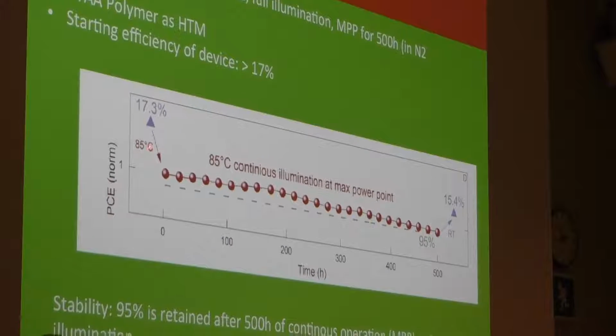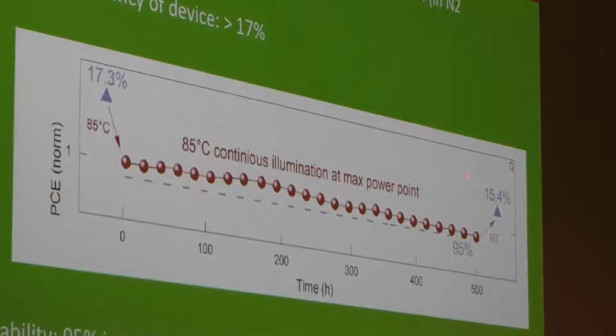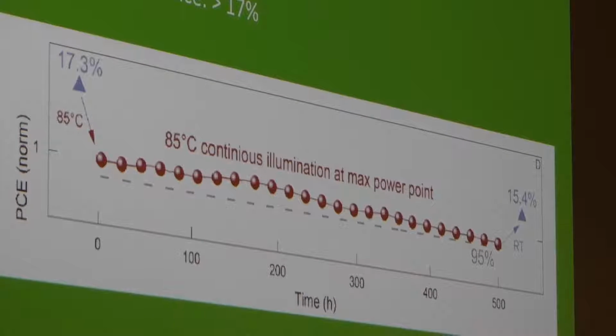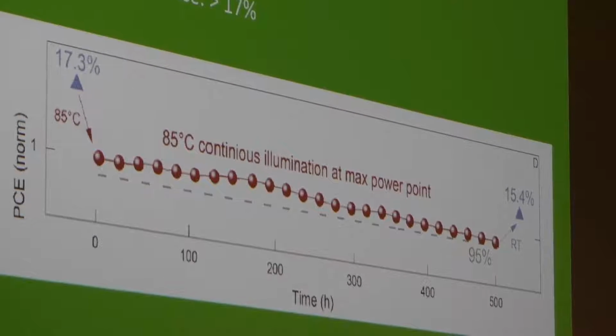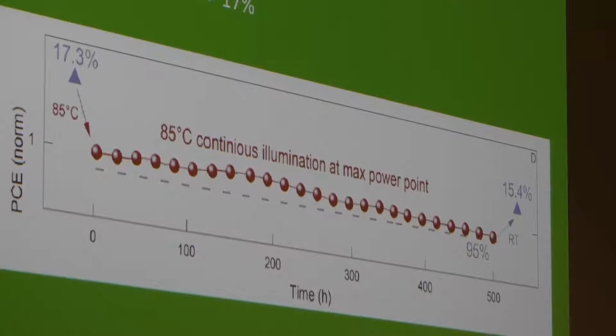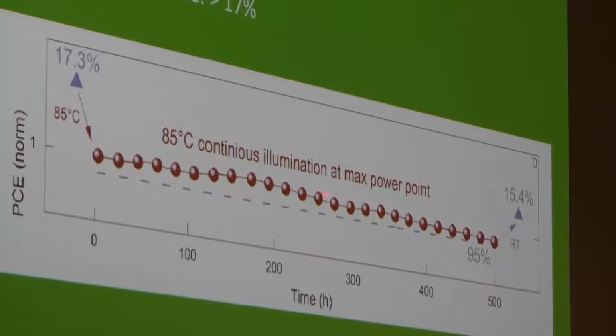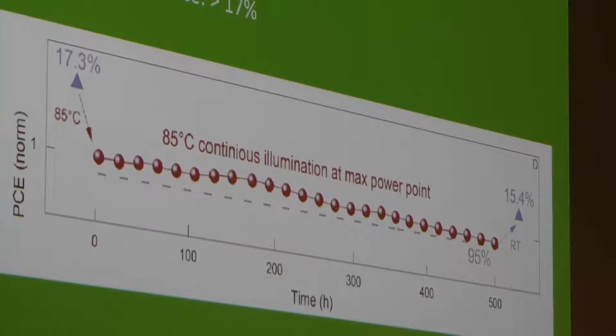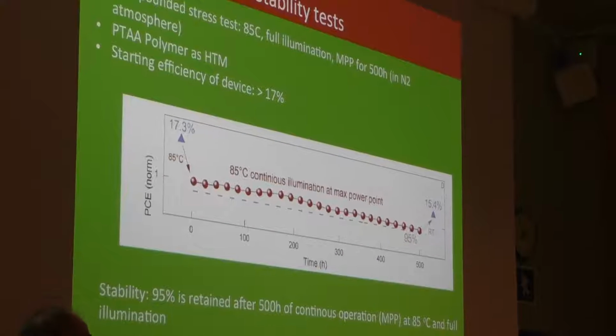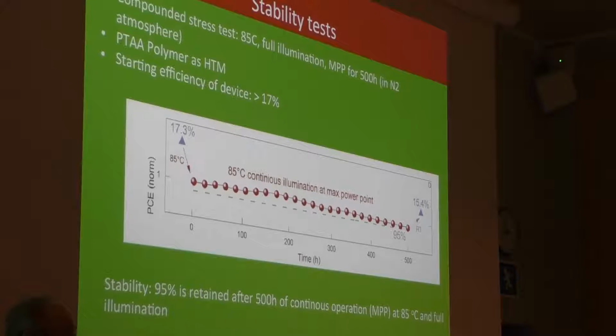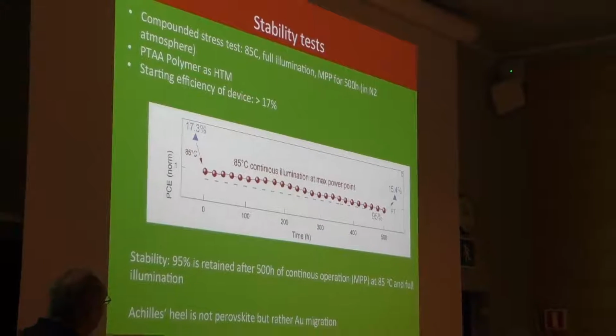So it's 85 degrees now, it's 500 hours, full sunlight and operating all the time. So it is as tough as we can do it according to protocol. And you see the stability is very nice here. And this is now using a polymer instead of Spiro. That is the trick to get the stability. So I think now at least we can say that the perovskite solar cell is not unstable, as people have said for a long time. They can be stable, we think. Of course, more work needs to be done here, but this is encouraging.